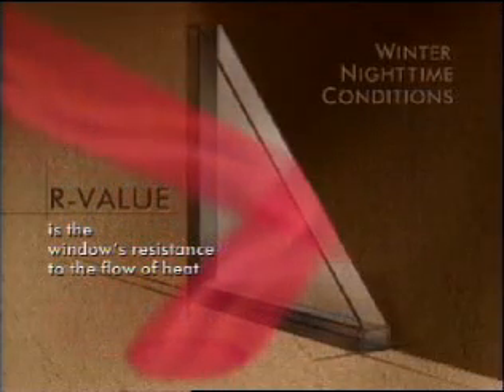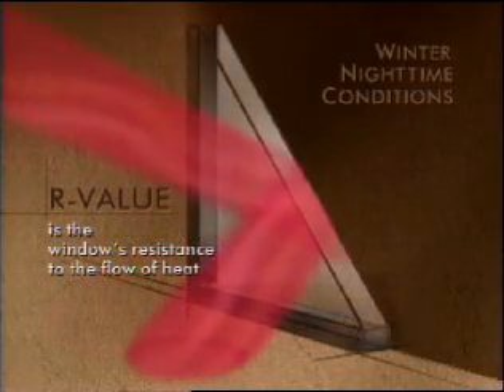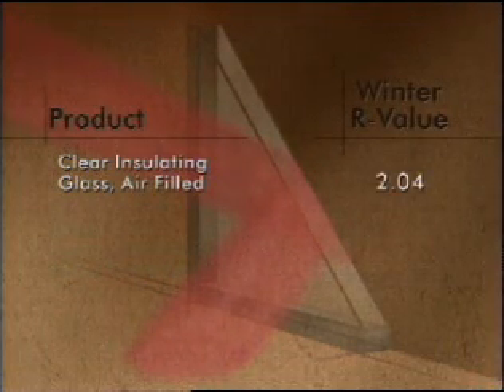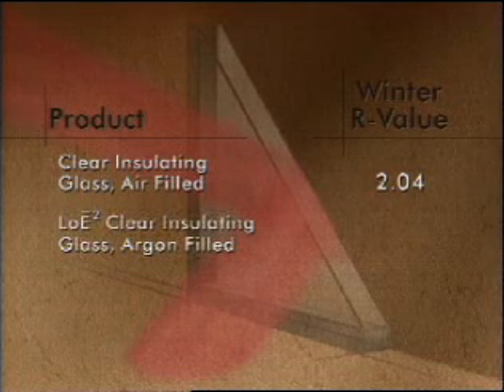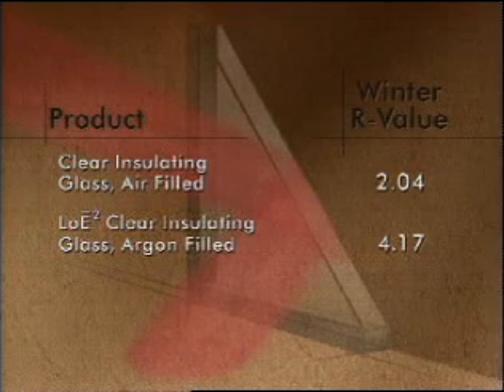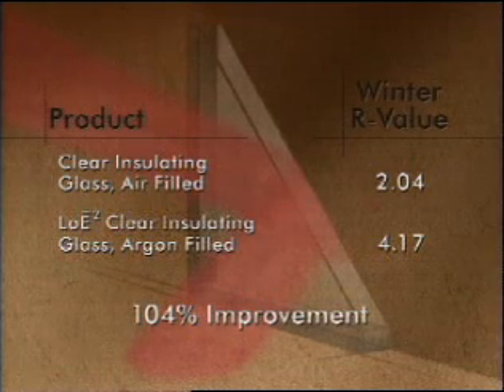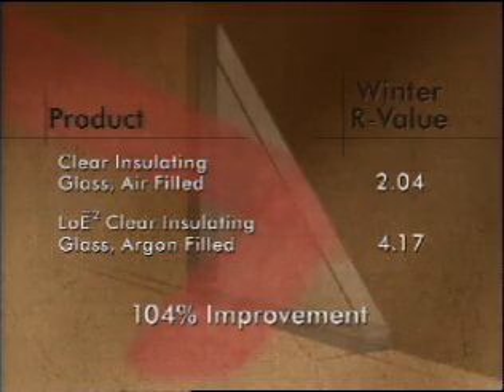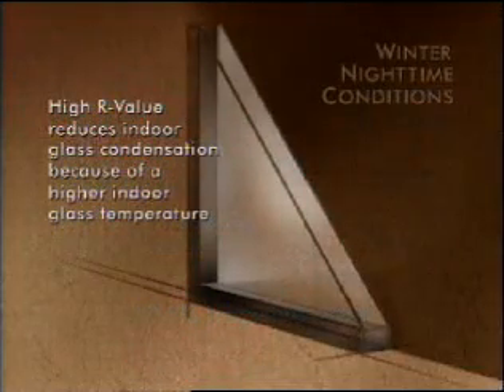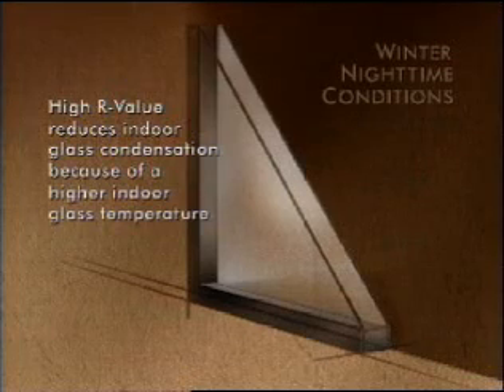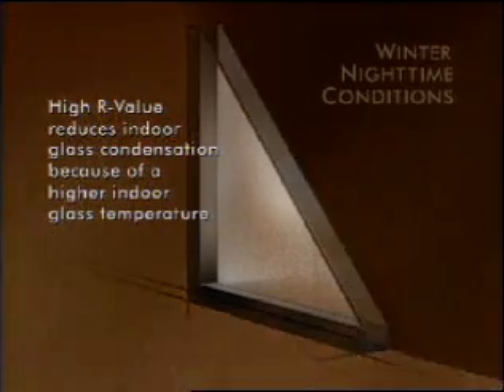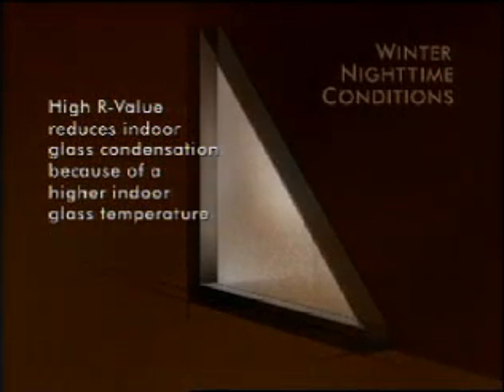The R value is the window's resistance to the flow of heat. The winter R value for a clear, air-filled insulating glass unit is 2.04. The winter R value for a LoE² argon-filled insulating glass unit is 4.17, a 104% improvement. Look for windows with insulating glass products that have low U values and high R values. Using LoE² glass products in a window with a high R value also reduces the likelihood of indoor condensation forming on a window because it produces a higher wintertime indoor glass temperature.